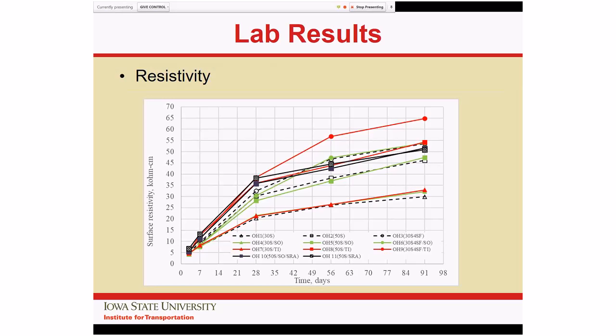And so you can see that if we have a system with a high resistivity, it means that it's going to be a lot harder for the water to get through. It's a bit of an indirect measure, but if there is a higher resistivity, there is less fluid in the system, and that's a good thing. That's fundamentally what we're trying to do.